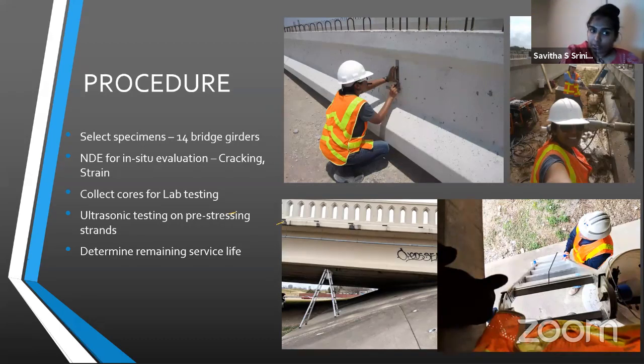And the next step was to do ultrasonic testing on pre-stressing strands that were undergoing corrosion. And with all of this information, the end result was to find out what's the remaining service life on these structures.